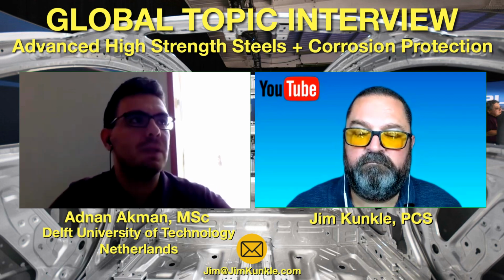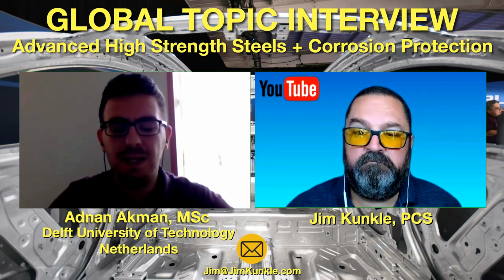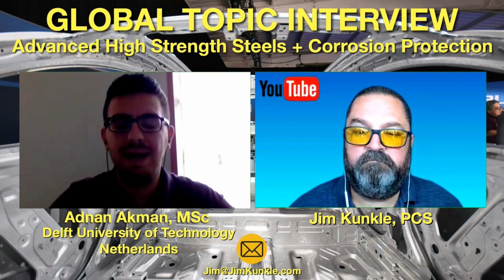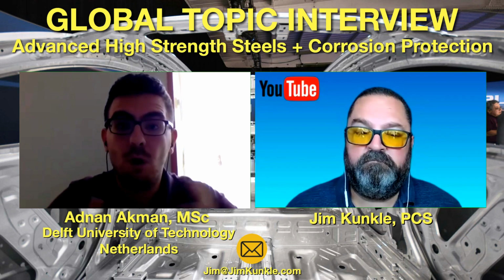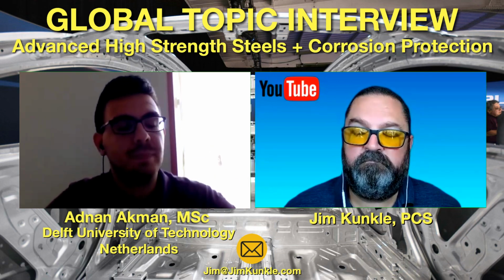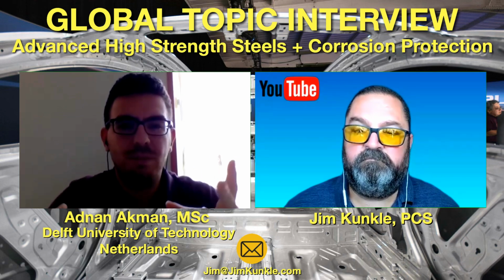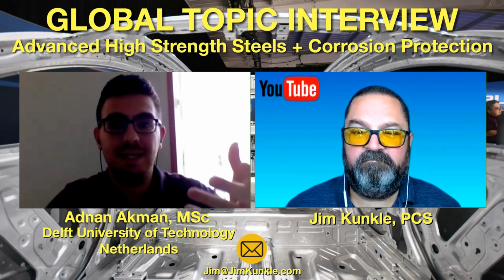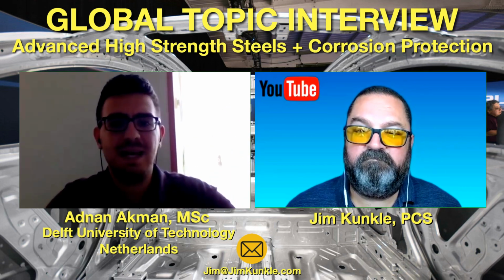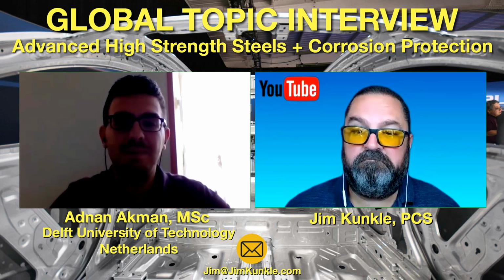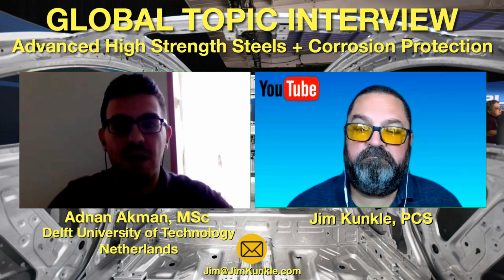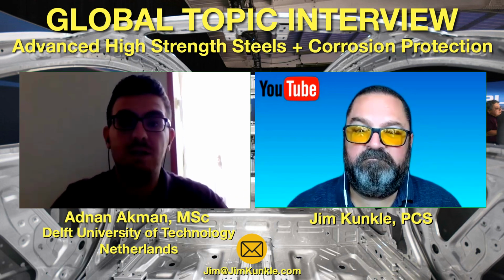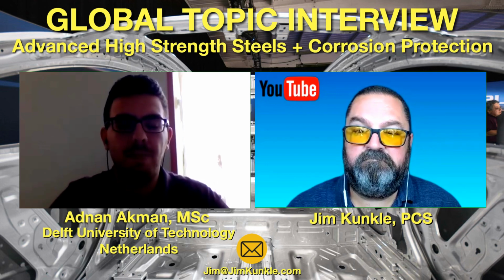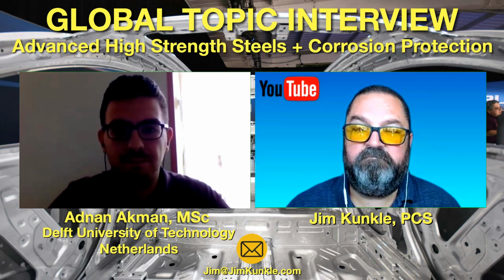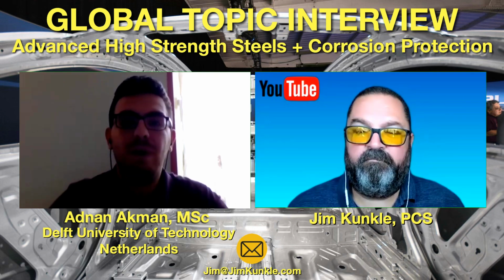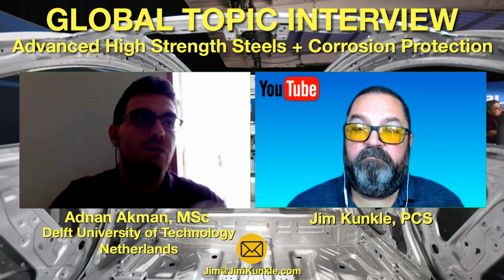In addition to them, there is a technique called hot stamping, also called hot forming. It is a quite novel technique, and it is used a lot nowadays to form complex geometries with advanced high-strength steels. The main idea, as you can understand from its name, is hot forming. Your steel is at high temperatures, and at that stage, they form it, and at the same time, they quench it to give a final microstructure. This technique is quite popular to form complex geometries. So improvement in the thermomechanical processes helps us to form lightweight complex geometries for advanced high-strength steels and for the automotive industry.